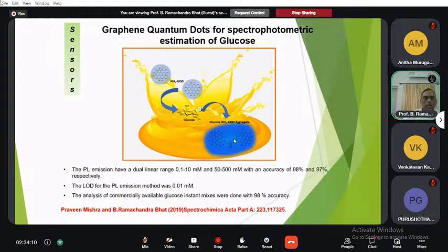observed, and this has a dual linear range of 0.1 to 10 millimoles and 50 to 500 millimoles, with an accuracy of 98% and 97%. So the limit of detection for this PL emission method was 0.01 millimole, and the analysis of commercially available glucose in an instant mixture was done with a 98% accuracy, and it has been published in Spectrochimica